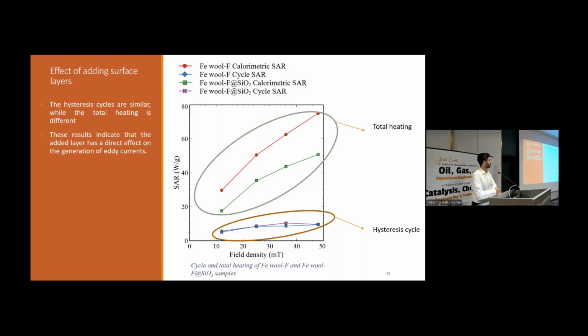So what we can see here is that adding this coating has no effect on the magnetic properties of iron wool and has no effect on the hysteresis cycles. But it has a big effect on the total heating. So what we can conclude is that it has a really detrimental effect on the generation of eddy currents. And we think it's due to the fact that silica is not a conductor. And so when we add it on the surface layer of our iron wool, it's going to hinder the creation of eddy currents, and thus that's why we're seeing this detrimental effect on the total heating of our samples.